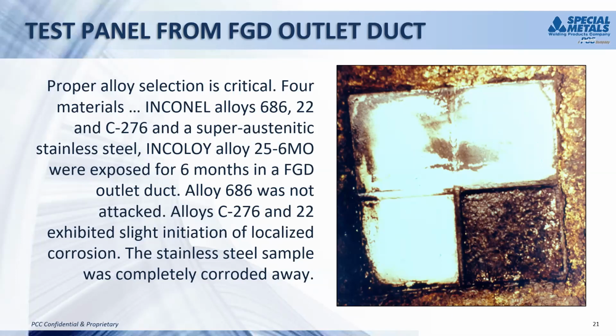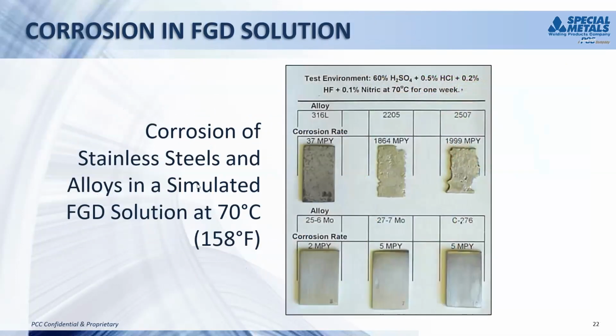So it just shows that a higher alloy, when it's required, even in a thinner section, provides much better resistance. The next slide shows another way that materials can be evaluated for FGD systems. In this case, it was a laboratory study. This is a very aggressive environment, obviously, but we estimated that it might be similar to what would exist under a deposit in an operating system.